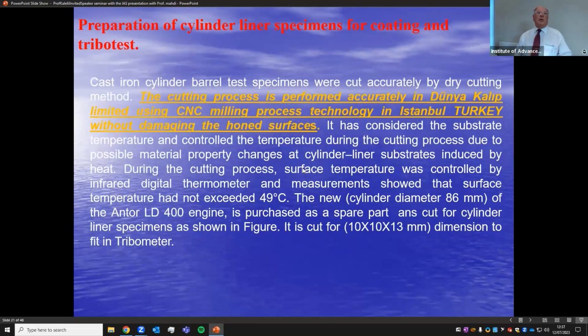And the cutting process. So we collaborated with industry. I have a good collaboration with Dünya Kalip Limited in Turkey, and they used CNC milling technology without damaging the honed surface. They measured the temperature, not exceeding 49 degrees Celsius, and they cut in a dry cutting process. And they cut very well, 10x10x13 millimeter dimension, and it fits well in our tribometer.